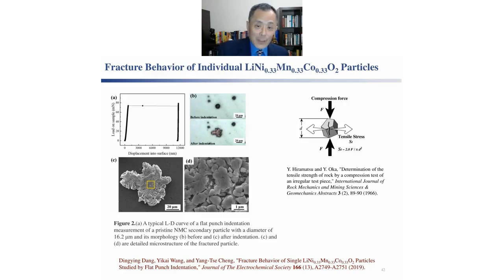And this is an example of such a measurement. We first find the individual particle and then load it with our flat punch indenter. At some force, the particle would crumble, and that is defined as our critical compression force for fracturing this particle. And we can actually look at the fractured particle, and most of the fracture is occurring between the grain boundaries, but there's also intragranular fracture that can occur in the particles.